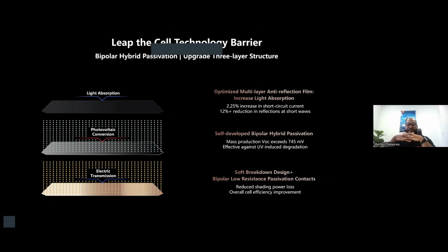That is a 2.25% increase in short circuit current and a 12% plus reduction in reflection at short waves, because you can see there's no reflection, the busbar is clean at the front. But then also the self-developed bipolar hybrid passivation. I mentioned also the mass production VOC increased to 745 millivolts, effective against UV-induced degradation. Then we have what we call the soft breakdown design plus the bipolar low resistance passivation contact, which reduces shading power loss. Overall cell efficiency is also improved on these cells of ours.